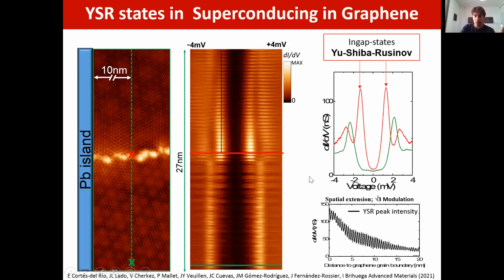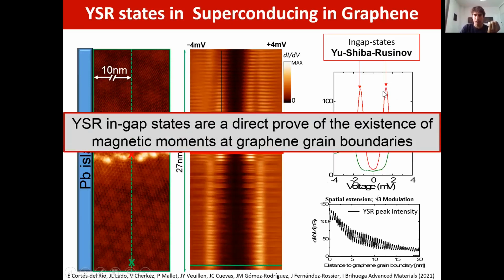Also very important, the existence of in-gap states tells us that there are magnetic moments on the grain boundaries. So this is a direct measurement that you have magnetic moments on grain boundaries. Otherwise, you cannot have states inside a superconducting gap.